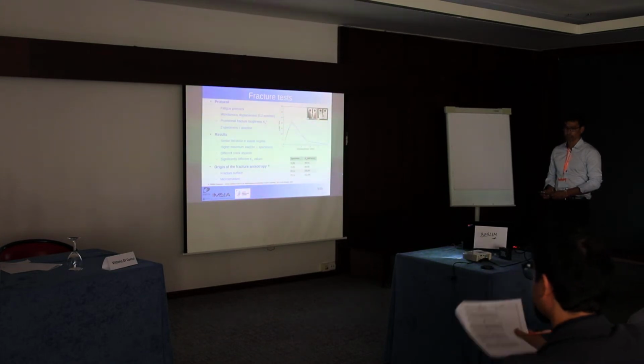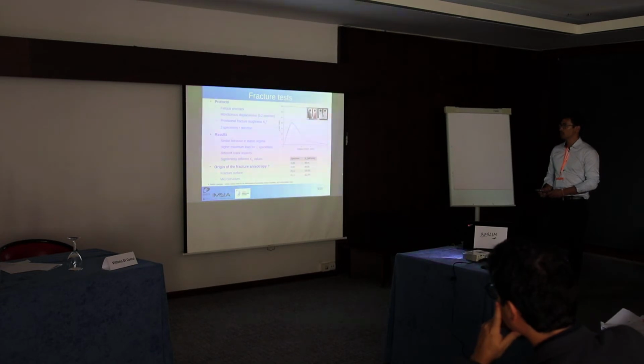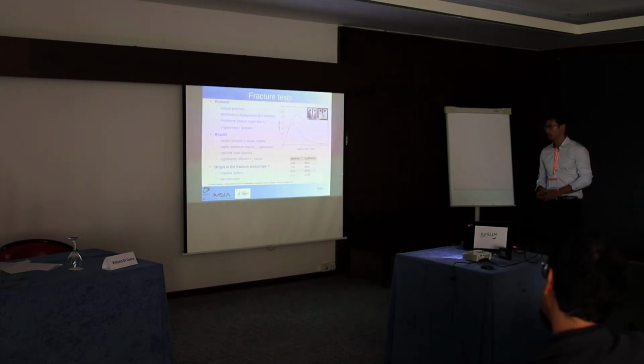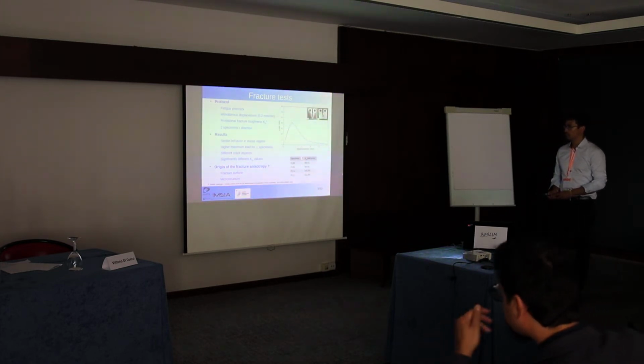Now, as we have already seen, there is a higher maximum load for the perpendicular specimens, so different loads in the two cases. We also see different crack aspects, with a straight crack in one case and a deflected crack in the other case, but we'll come back to this a little bit later. And finally, considering the KQ values that were computed, first of all, we have repeatable values, but we also find significant differences depending on the orientation.